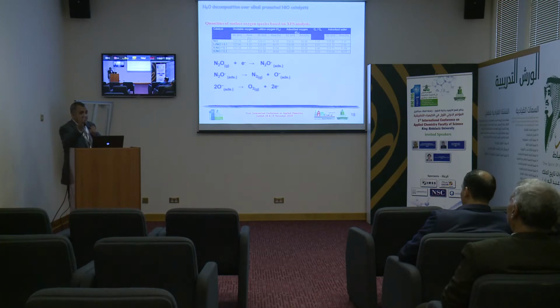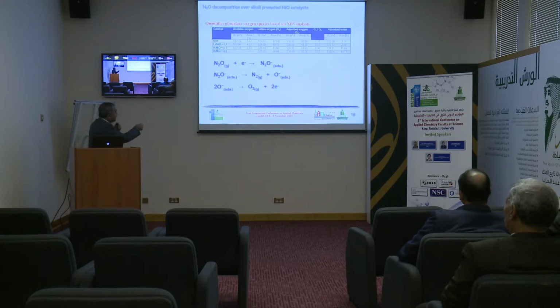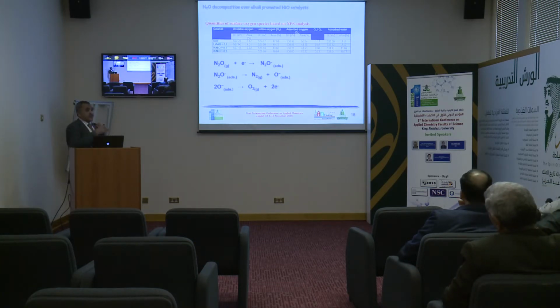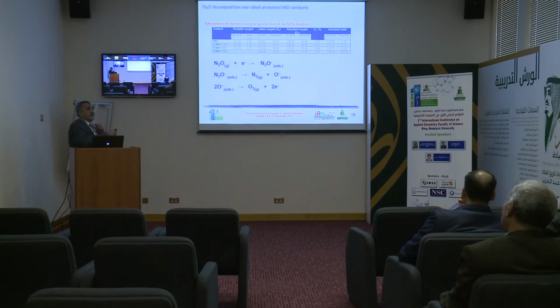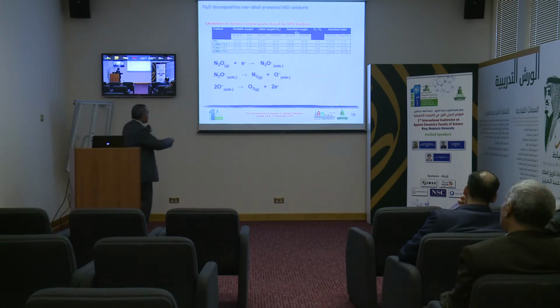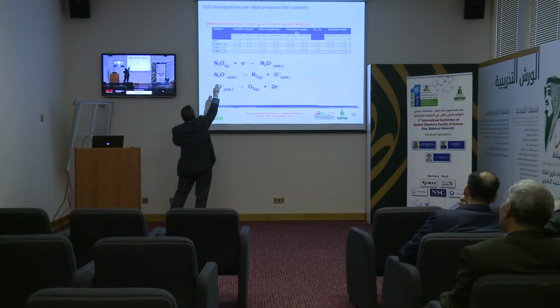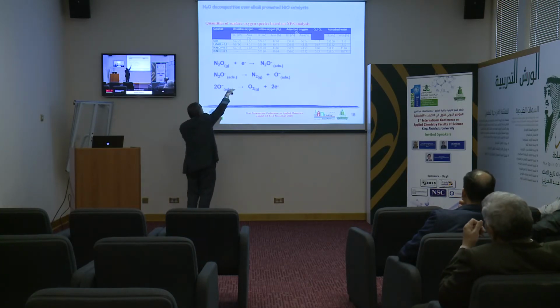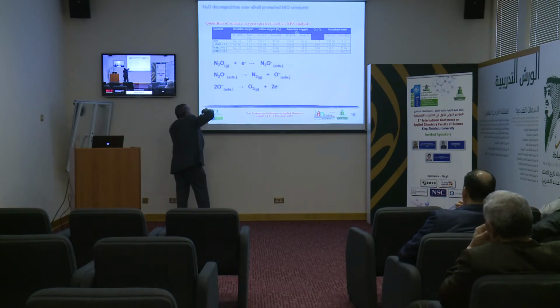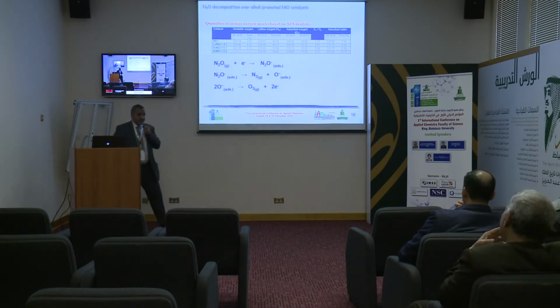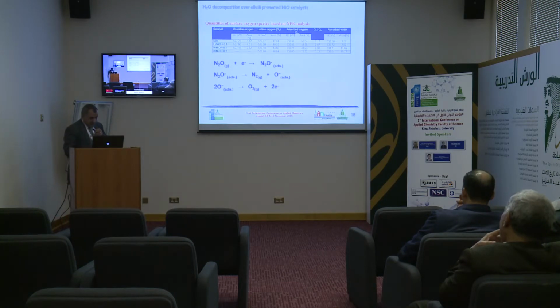If we are using bare nickel oxide, the adsorbed N2O will accumulate on the surface and stop the reaction. That's why the addition of alkali promoters enhances this reaction. And regarding the last step, from this table we can also observe that the lattice oxygen binding energy decreases, which means the ability of the catalyst to liberate oxygen is also enhanced by the presence of these added alkali cations.